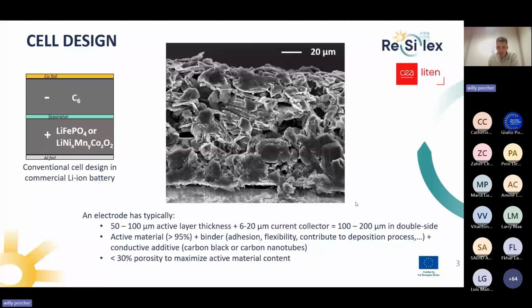So in an electrode, we also want to maximize active material content, to always minimize inactive components in the cell. It's really key to achieve high energy density cells. The active material is usually more than 95% of the electrode composition. And there is also a binder, which has many functions.